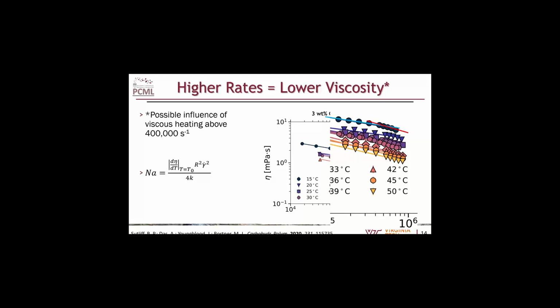The quick calculation for this is the Nahme-Griffith number, where you use the change in viscosity due to temperature, which we already gathered, your hydrodynamic radius, your shear rate, and the thermal conductivity of your water. Ideally you would use your actual suspension or solution thermal conductivity, but because we're 90+% water, and this was a back of the envelope calculation, we just estimated it as 0.6 watts per meter Kelvin, which is that of water at 25 Celsius.